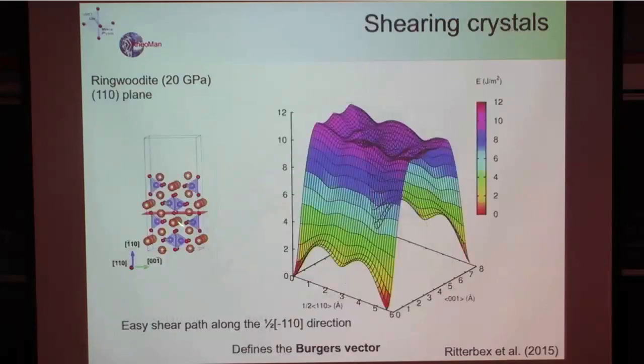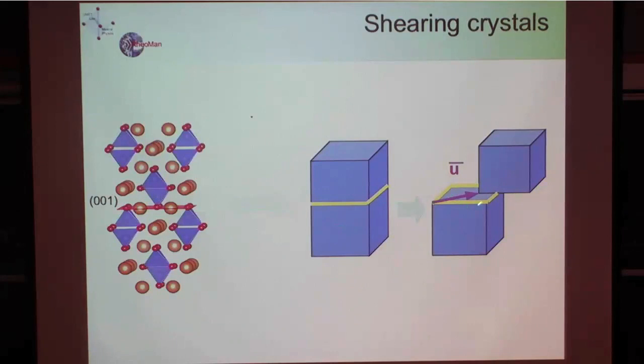It's a purely theoretical concept, and it's made like that. You take the crystal structure and apply it step by step: you mesh your plane, you apply a vector inside the plane, then you impose this displacement in the plane. You let the displacement perpendicular to the plane relax freely. You relax the structure and you calculate the converged energy. It's a purely theoretical concept. This is not something that you can measure.